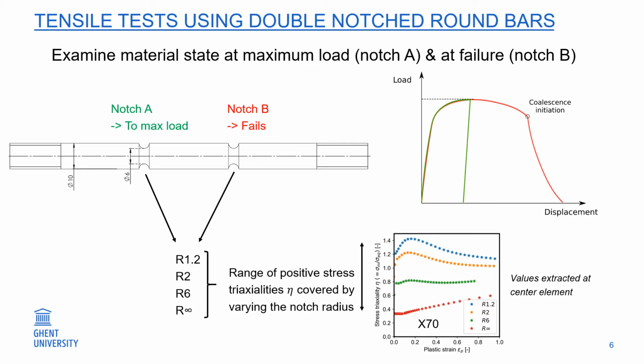The advantage here is that we can investigate the damage state at maximum load and at failure with only one tensile test. This is in particular interesting for the tensile test on hydrogen charged specimens, since hydrogen damage might already be visible at maximum load. By using notches with different radiuses, different stress triaxialities will be induced inside the specimen. As a preliminary numerical study indicated, a broad range of positive stress triaxialities is covered by these four notch radiuses.